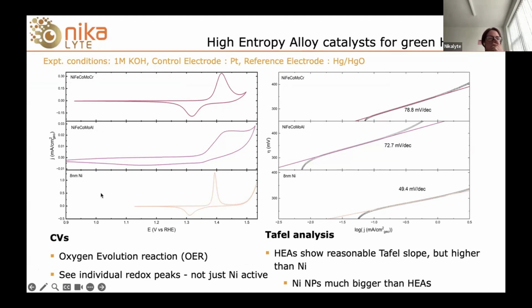So what was very interesting is that nickel is known to be an active catalyst, but what we wanted to see was how do these high entropy alloys compare to nickel, and are we seeing other elements in that alloy being catalytically active, or is it just the nickel that's doing the catalytic reaction? And what we can see from these CV sweeps is that we are seeing oxygen evolution reaction. We're seeing oxidation reduction peaks, which are not in the same place as just the bare nickel. So we are seeing contributions from other parts of the structure.